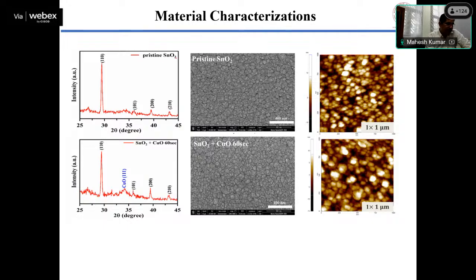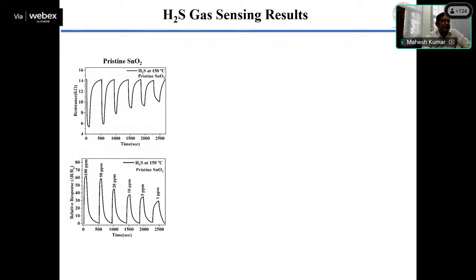By characterization with XRD, we confirmed this is tin oxide. Also, when we decorated copper oxide for 60 seconds, we got a small hump. We also confirmed this by EDX and XPS. Because the deposition is only 60 seconds, the copper oxide thickness is very small, so in XRD we do not get a high peak, because the thickness is not sufficient to give a signal from copper oxide. This is the pristine sample.